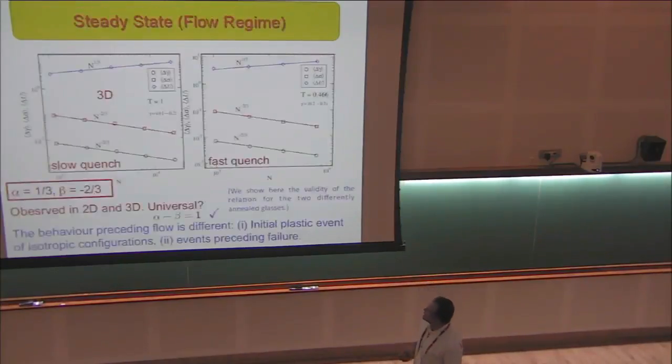And these relations are indeed observed in simulations, and they seem to have the same fairly nice looking values in 2 and 3 dimensions. Whether they're universal and how one can obtain these numbers is a point of study. But this behavior is different from what happens if I were to take a fresh glass sample that has been cooled down into a solid state, and I apply external stress.